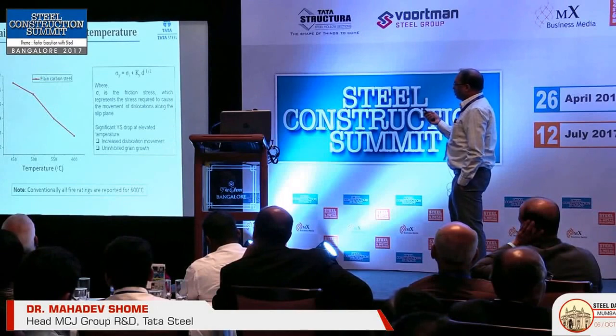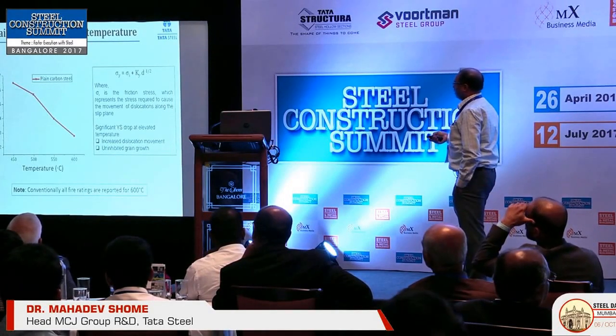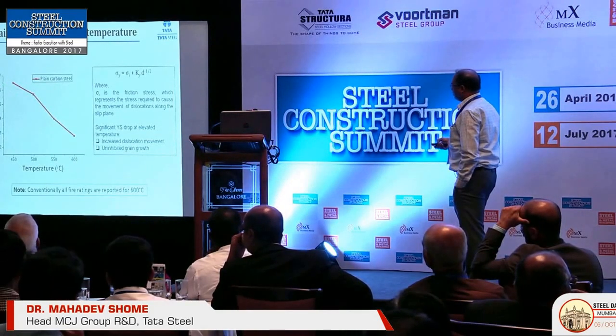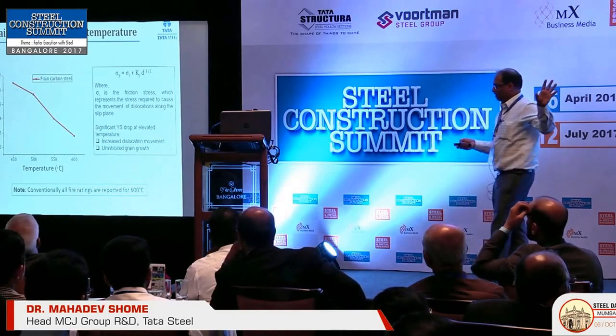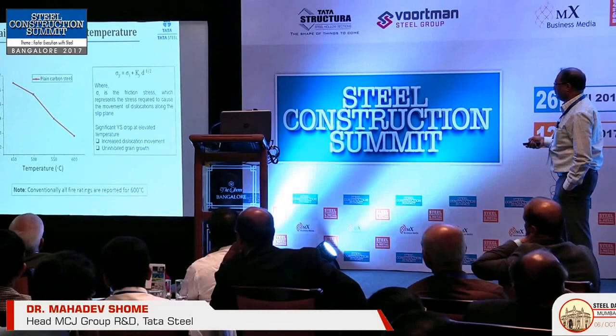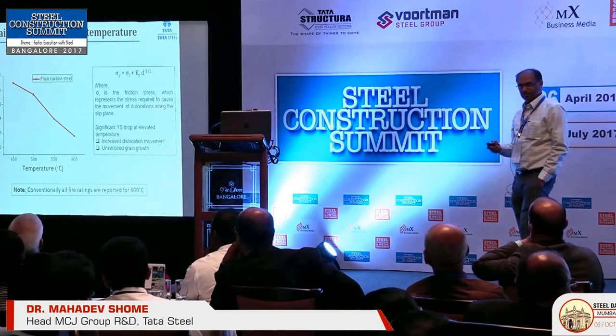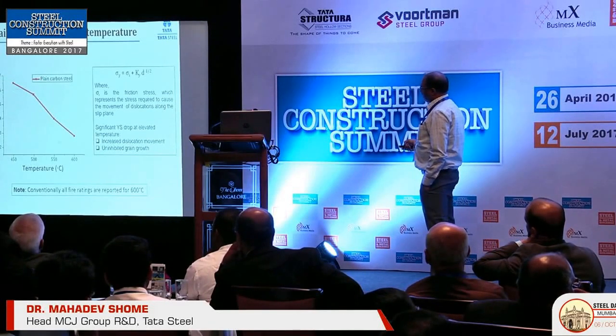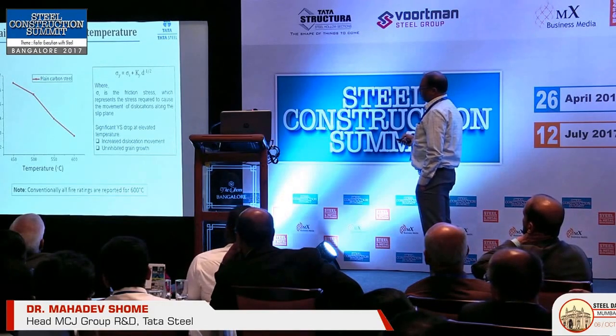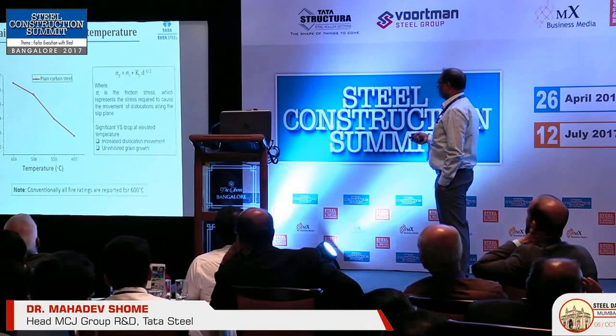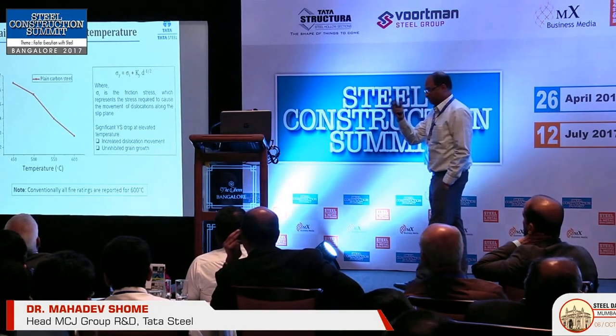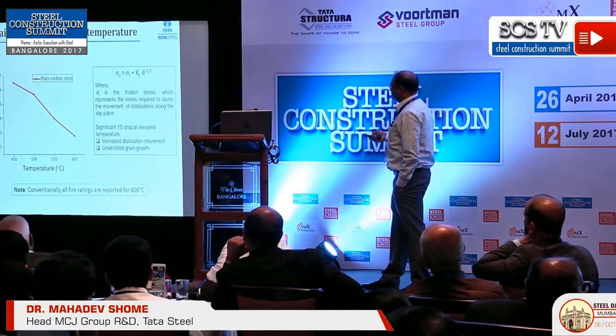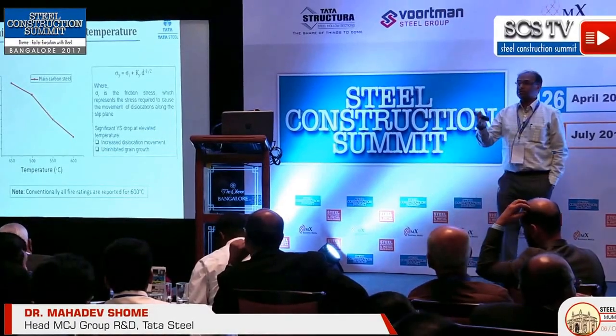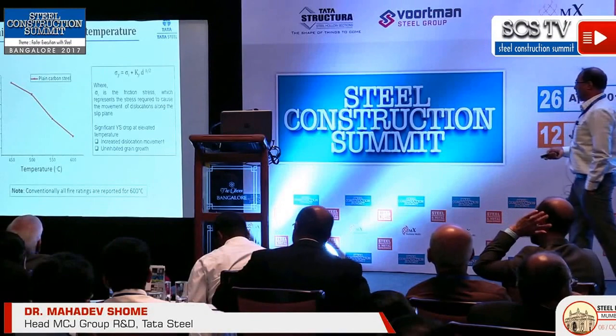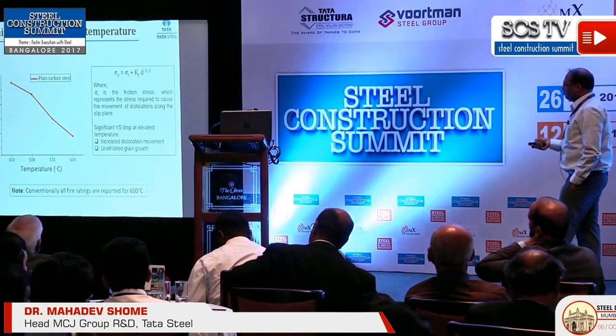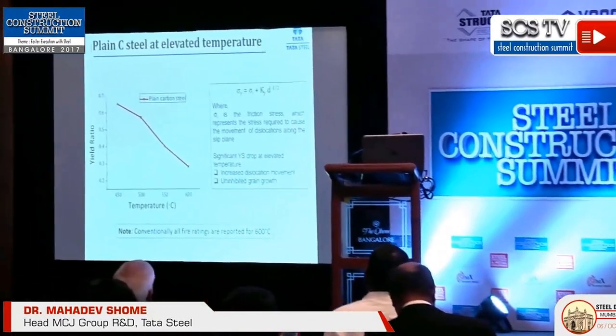Now, how does the fire resistant steel differ from the plain carbon steels or the normal steels that are available? That in case of a fire at 600 degrees centigrade, there's a bit of metallurgy, but it will be simple to understand. The yield strength falls. The yield ratio comes down to less than 0.3. And the yield strength is basically represented by this very famous Hall-Petch equation, where this is the frictional stress, and this is the Petch parameter, and this is the grain size. Steels have grains inside. Now, this is determined by the dislocations, how fluid the dislocations are inside. These are defects in any steel materials. Now, if you are able to inhibit movement of these dislocations, you can get very high yield strengths, and that is how the yield strength is maintained.